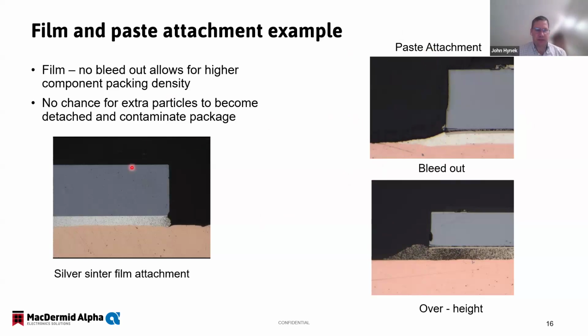One of the big advantages too is with the lack of excess material here, there is no chance for these extra particles to become detached, where you can see here in a further operation that this material, if you bumped into it or something happened, you could see this material detaching and then becoming a contaminant somewhere else in your process.